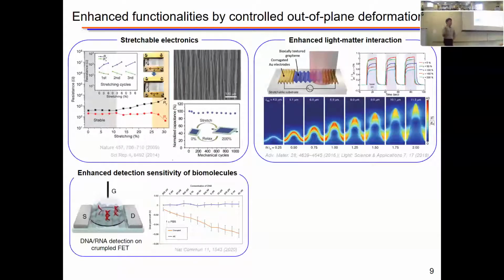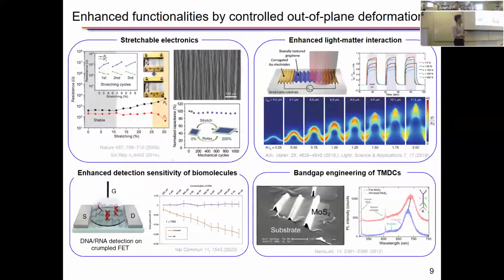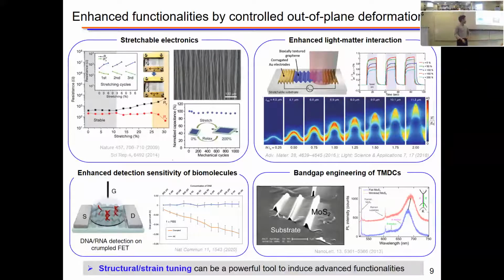Another interesting area is when we integrate this type of wrinkle structure into a field effect transistor. It is reported to achieve one of the highest detection sensitivities of biomolecules, resulting from the formation of electron hotspots at the belly of the wrinkles. Another popular area is that with mechanical strain, we can tune the electronic band structure, especially for semiconductor materials like transition metal dichalcogenides, which I'm going to talk about in a later slide. And this is one of the popular areas called band gap engineering. So we know that structural or strain tuning can be effective too, and it's in use for advanced functionalities.